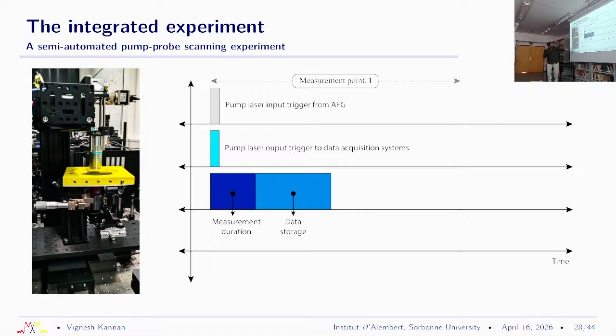I'm not going to go into details here, but we have a full semi-automated Python code that controls the entire experiment. We generate a pump laser pulse, which triggers the laser source onto your excitation point. We make a measurement of the particle velocity as a function of time at a given spatial position. We then instruct the scanning stages to move by a given amount, to move my entire stage by 10 microns, for example, and then I make a new measurement, and I can do this in a semi-automated fashion for about a full day, and that would give me something like 100,000 points. This is eventually moving towards a fully automated system.